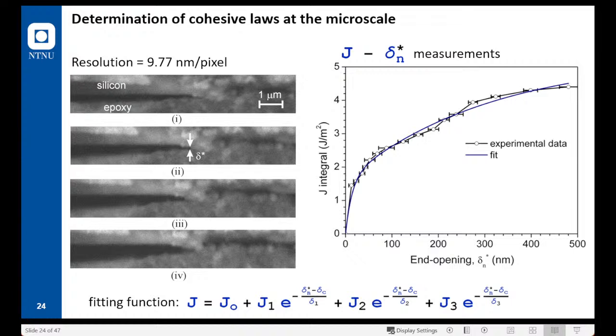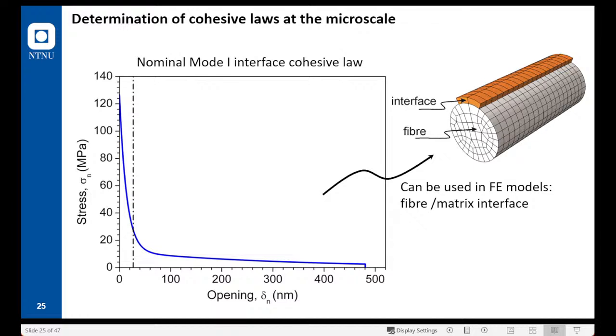We can also extract the cohesive law at the sub-micron scale. I have used the same fixture as before, and I have used a silicon plate to model the surface of a glass fiber attached to the epoxy. So in principle, we examine the cohesive law between the fiber and matrix. Again, we increase the load and we record the end opening and the J integral. And the derivative of that will give us the cohesive law at the interface, which can be used in a finite element code.